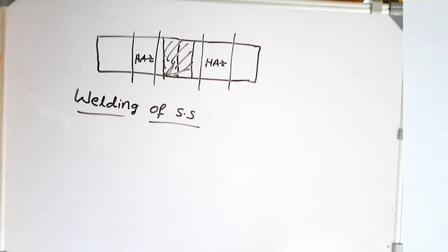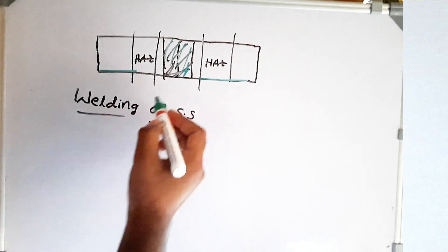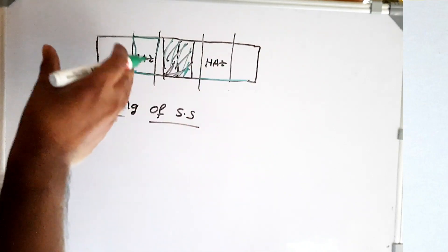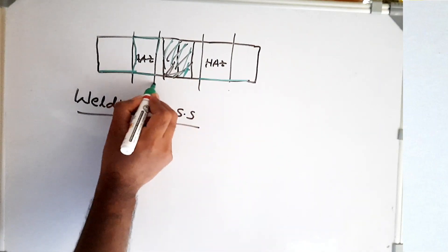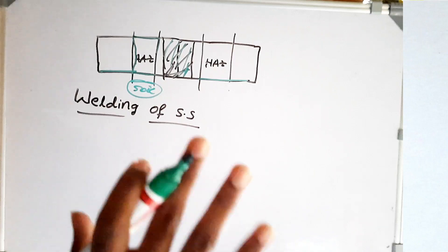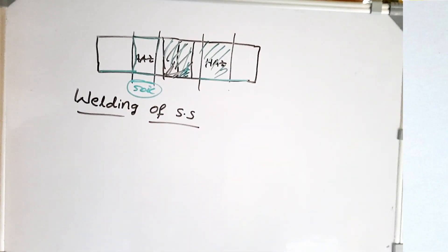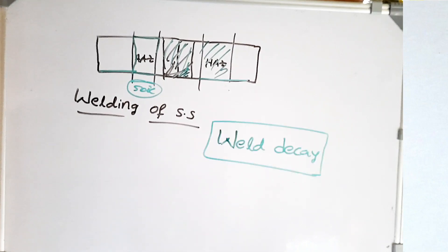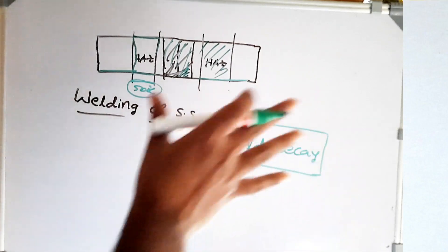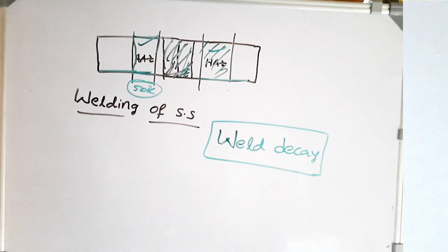If we have cooled our stainless steel quickly, there is no chromium carbide precipitation at the grain boundaries. But when welding two 18/8 stainless steel pieces, the heat affected zone away from the fusion zone also gets heated. If the temperature in this region reaches 500°C, chromium carbide formation occurs. So even though we avoided chromium carbide by fast cooling, during welding the heat affected zone develops chromium carbide precipitation, causing localized corrosion and reduced weld strength. If sensitization occurs during welding in the heat affected zone, we call it weld decay.